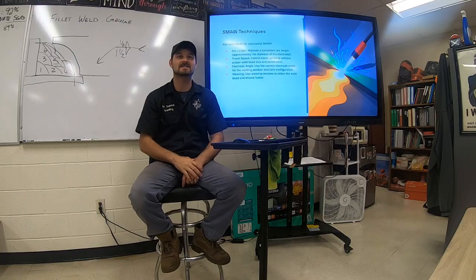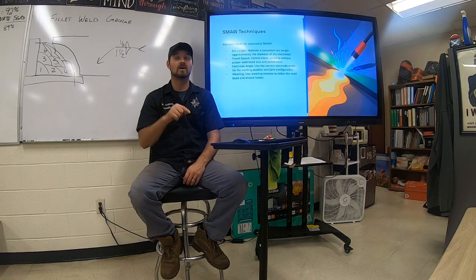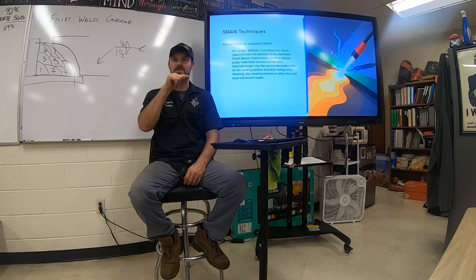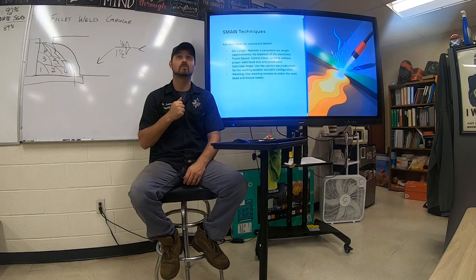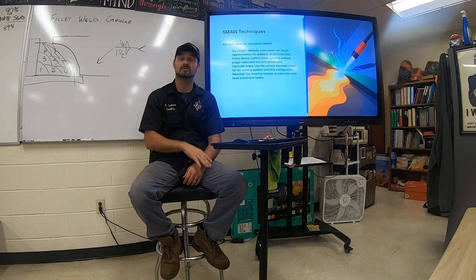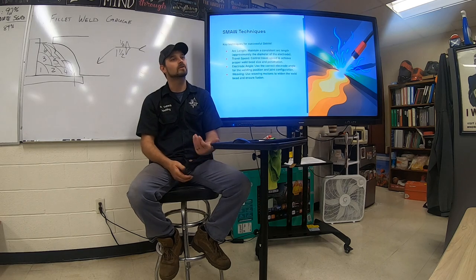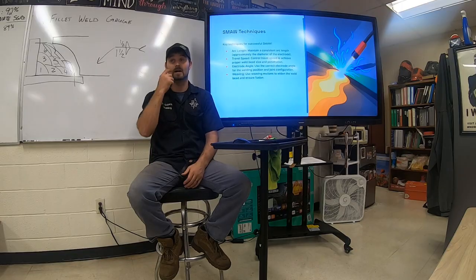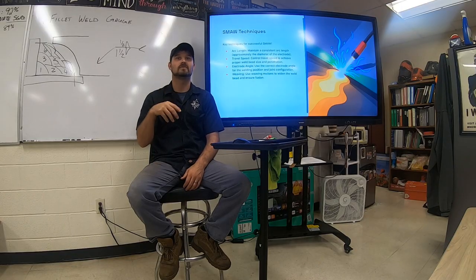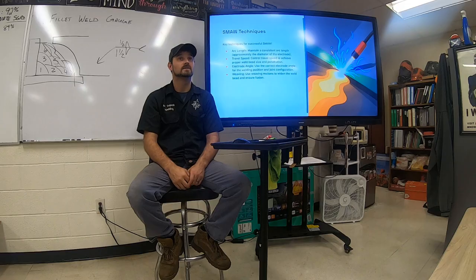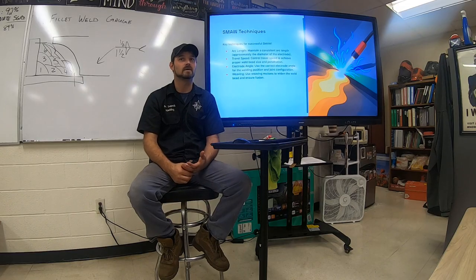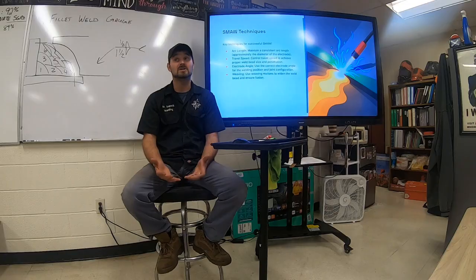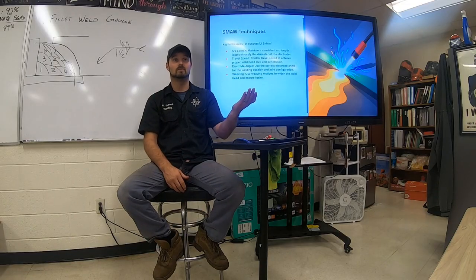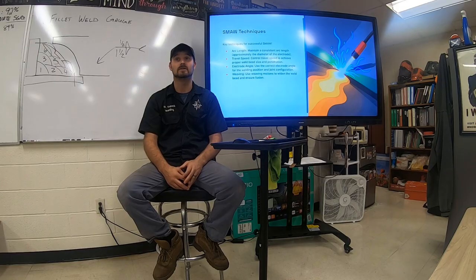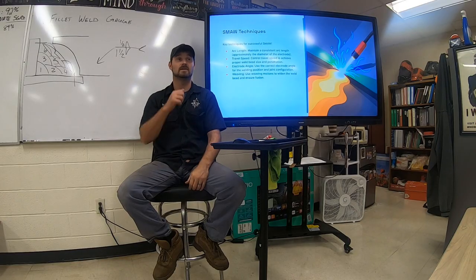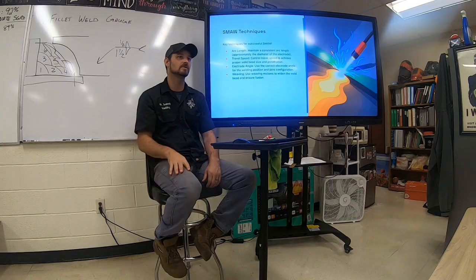If we have too fast of a travel speed, okay, our weld is gonna be real pointy, okay? You're gonna see that your weld is gonna be real pointy, and if we're welding really hot with that too fast of a travel speed, now we can get what's called undercut on the toes of our welds. That undercut is because we're going too fast and we're not giving that weld the opportunity to fill in, right, and create that weld. Our travel speed can be too slow. Remember, more weld the better is not always good. You know, we can put too much heat in, we can distort our material, we can crack our materials.